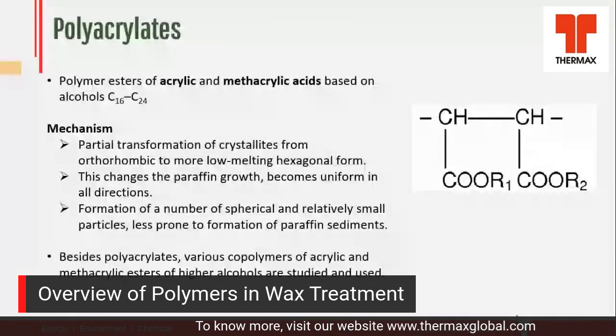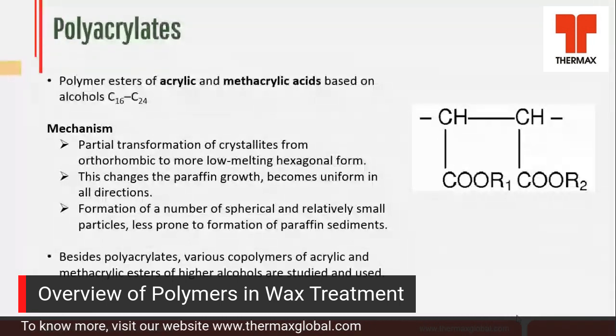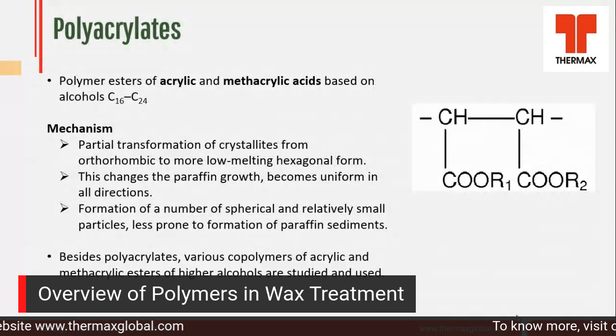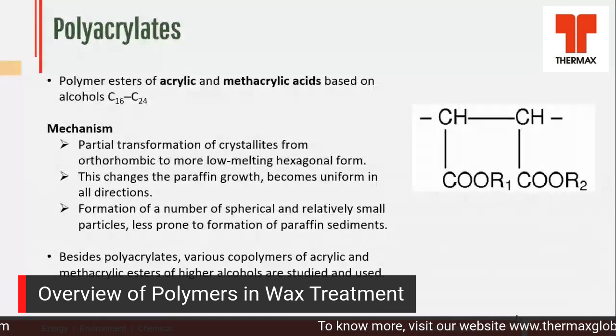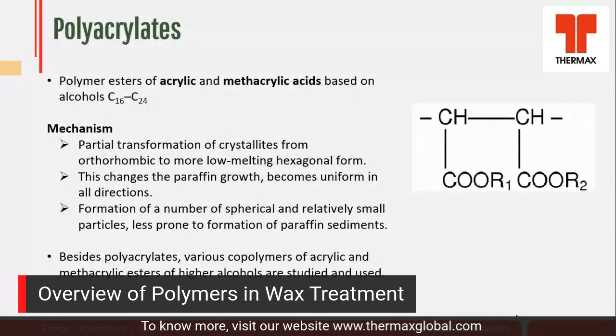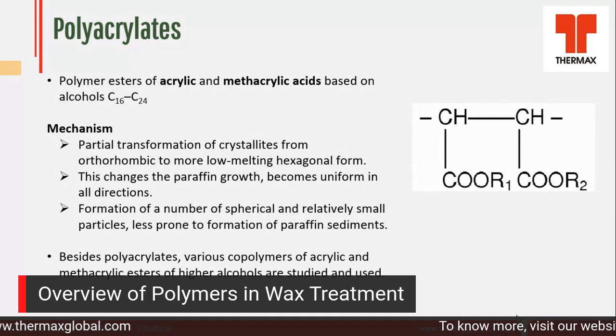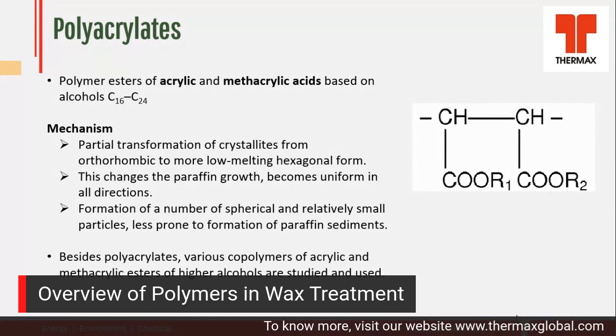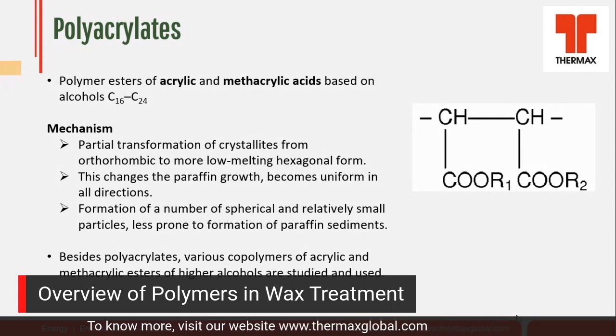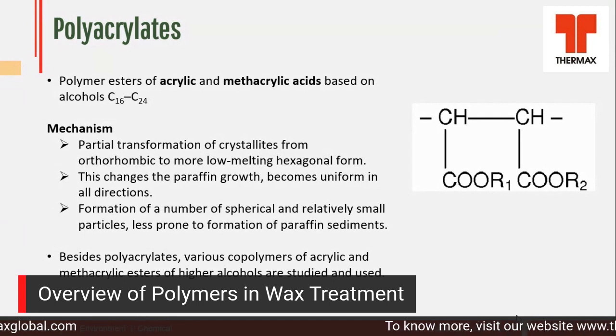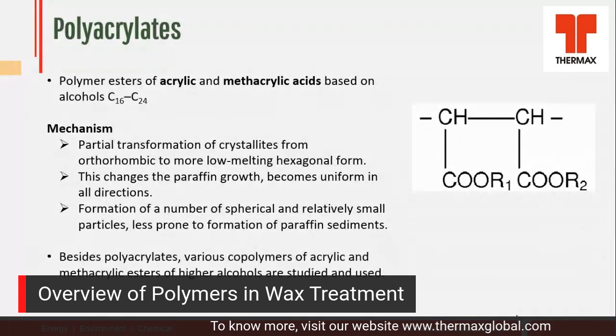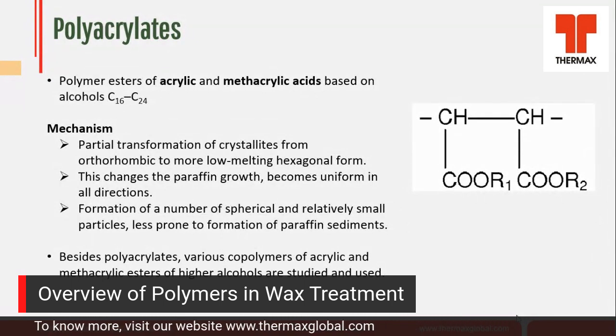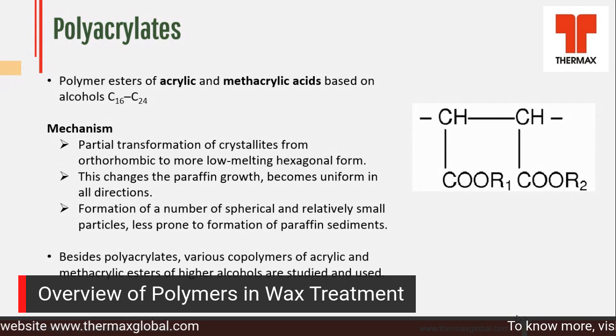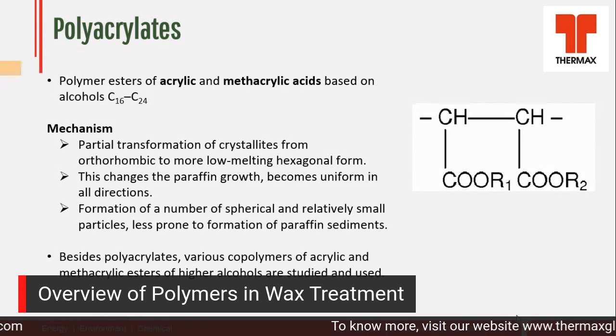Polyacrylate is also a very popular polymer used as a pour point depressant. They are not used as a flow improver, but for pour point depression they are the most popular. Here also, acrylic acid is esterified with fatty alcohol. They can be in the range of C16 to C24 for crude oil, and for lighter oil like lubricating oil or diesel oil, the carbon chain can be reduced further also. And then this ester is purified and then polymerized. This is also a pour point depressant, and the mechanism is the comb structure we discussed earlier.